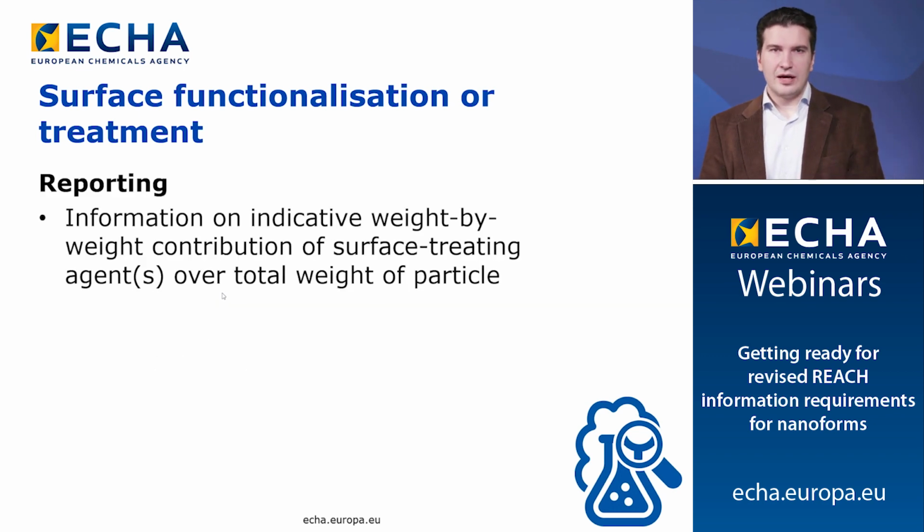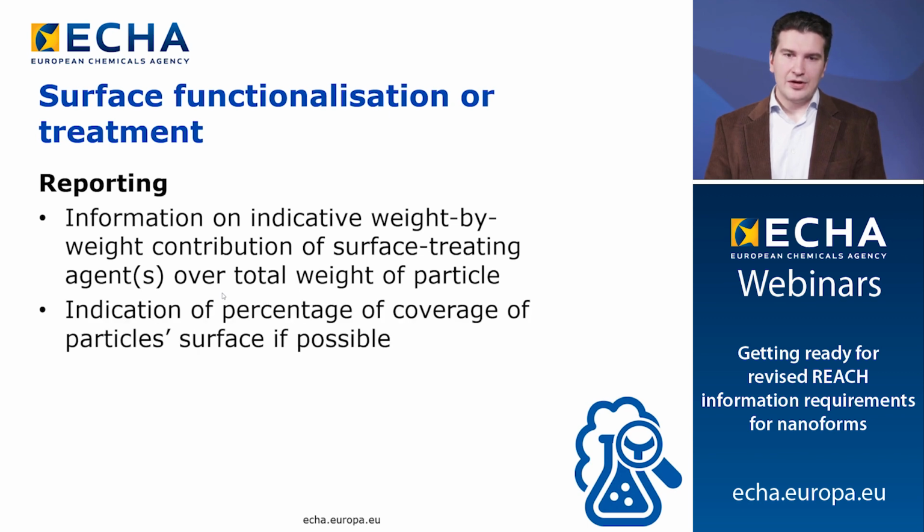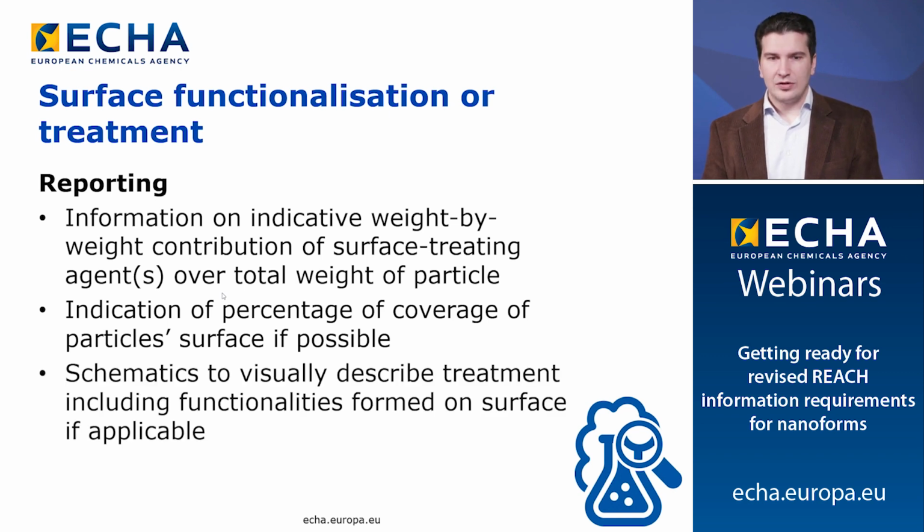In addition, we would want you to report information on the weight-by-weight contribution of the surface treating agents over the total weight of your particle. You need to give us information about the percentage coverage of the particle's surface, and you should, very importantly, give us a schematic that gives a visual description of the surface treatment, including the functionalities that are formed on the surface of the particles.